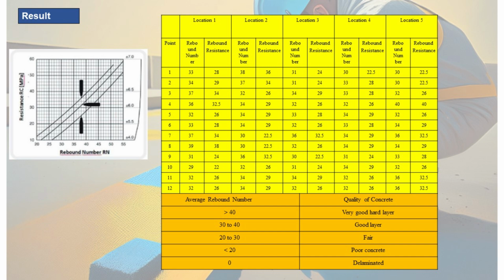32.33. Location 4, 32.67. And location 5, 33.75. These results indicate that the average rebound number for the tested concrete surfaces falls within the range of 30 to 40. This reflects a good quality concrete surface layer.